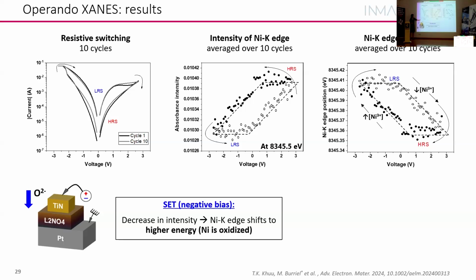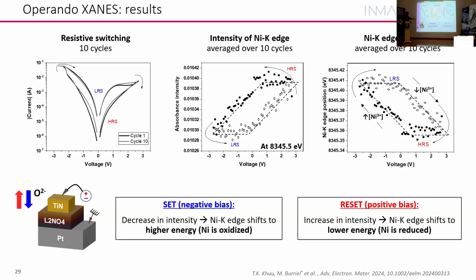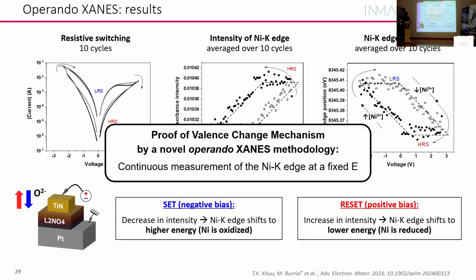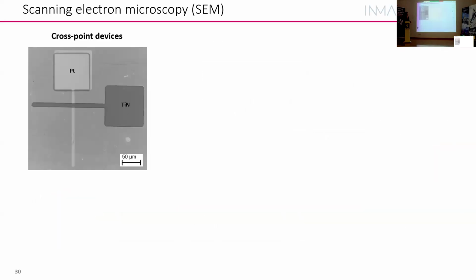Okay, so what happens when I apply a negative bias and I'm doing the set? Oxygen is coming into my sample. And we really prove this valence change mechanism because we measured experimentally that the nickel oxidation state was changing, and the opposite is happening when we apply, as could be expected, a positive potential: the oxygen comes out of the lanthanum nickelate and into the interlayer here. So yes, we prove this valence change by continuously measuring at this fixed energy.